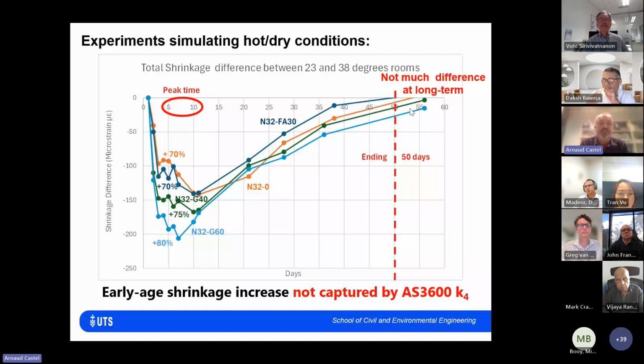So first thing, just as we do for durability, we know there's concrete that are performing very well against chloride. There's concrete that are not performing well. So it's the same thing for early-age cracking, restrained shrinkage early-age cracking. We need to select a suitable concrete that is likely to resist cracking very well in that case.